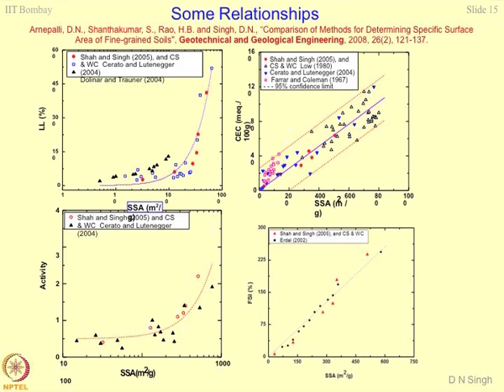SSA should include physico-chemico-mineralogical properties when soil comes in contact with contaminants. This activity is different from activity in classical geomechanics where only plasticity index and percentage clay fraction were considered. Truly speaking, this activity should be replaced by the word 'reactivity,' but we still need more time to prove it. SSA also correlates well with free swell index of the soil. So from SSA you can get liquid limit, activity, cation exchange capacity, and free swell index, or vice versa.